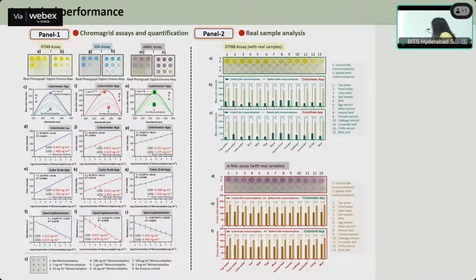So these are the results after plotting the data at different concentrations and also with the color graph. With different equipment, you will get a different kind of LOD. If you use the spectrophotometer, it is 1.3 nanograms. If you use the app, it's 0.56 nanograms. And if you use the colorimetric app, it's 0.49 nanograms.